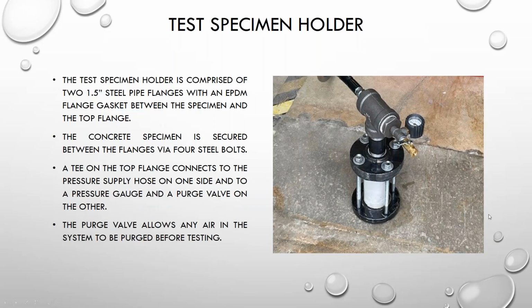The specimen holder consists of two 1.5-inch steel flanges. You see one on the top, one on the bottom, and there's an EPDM gasket between the top and the concrete specimen. The concrete specimen is held between the two flanges by 4 steel bolts. The T on the top has the pressure hose connected on one end, and on the other end we have the pressure gauge and a purge valve. The purge valve is to purge all the air that might be in the line before we start the test.